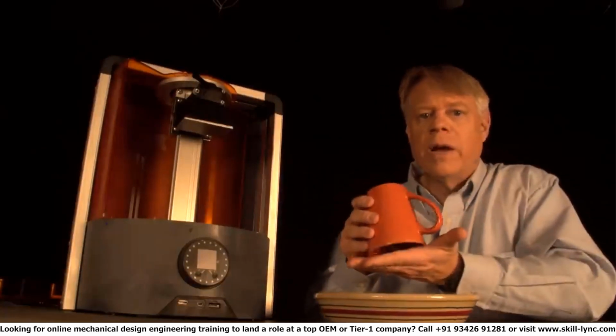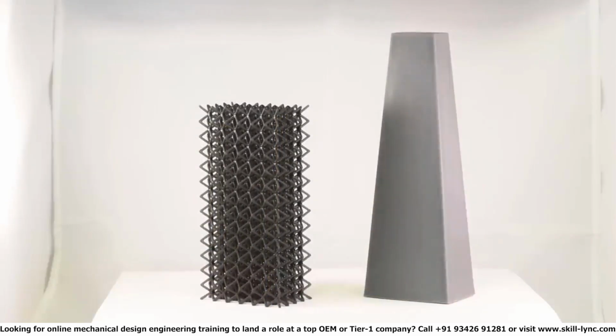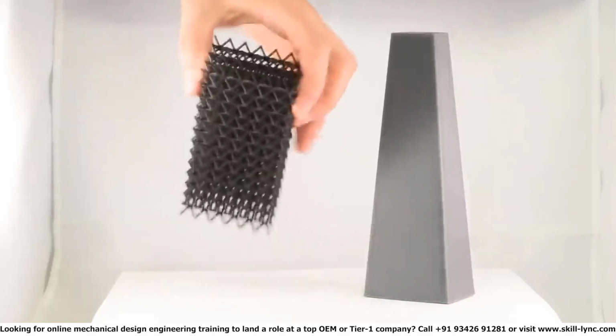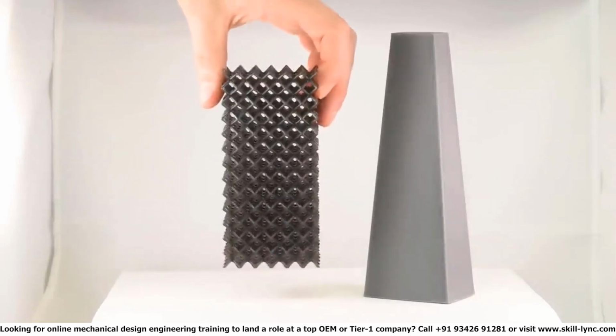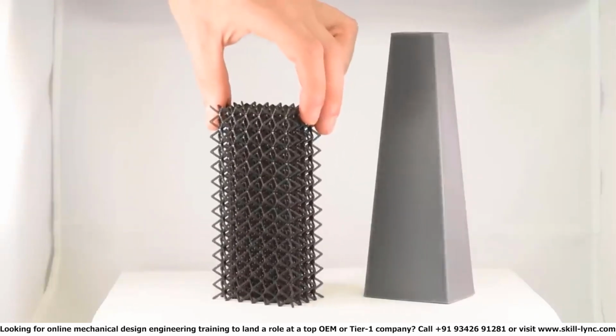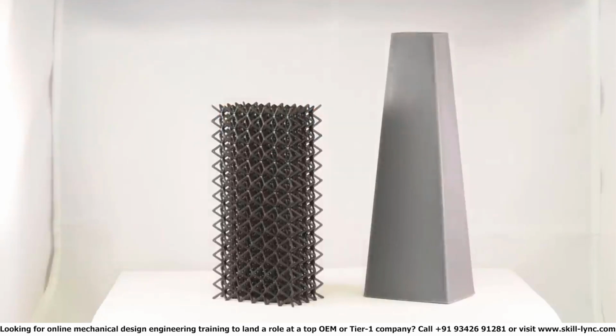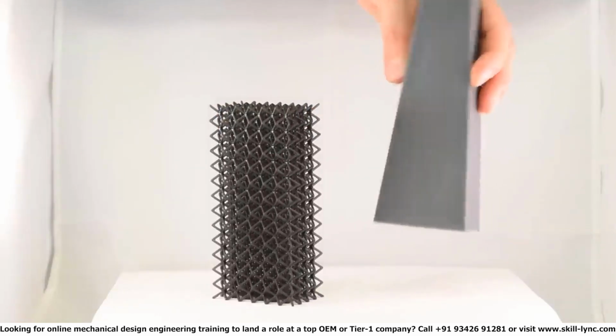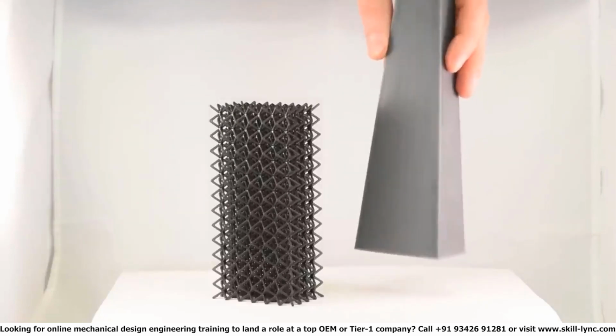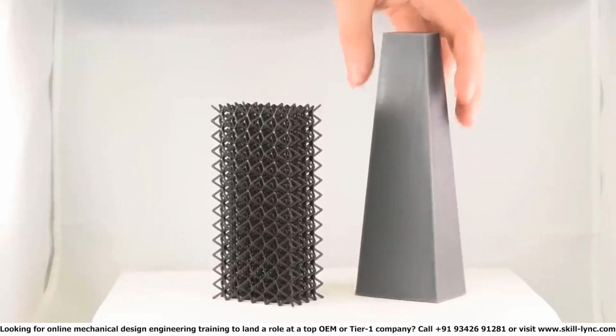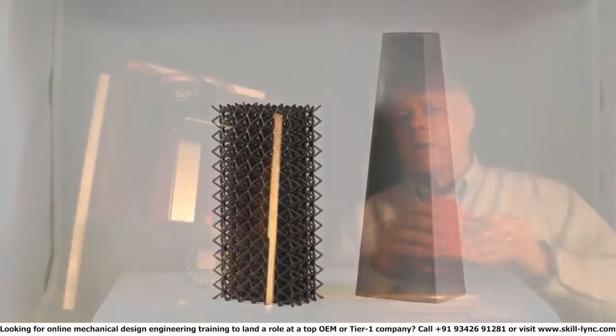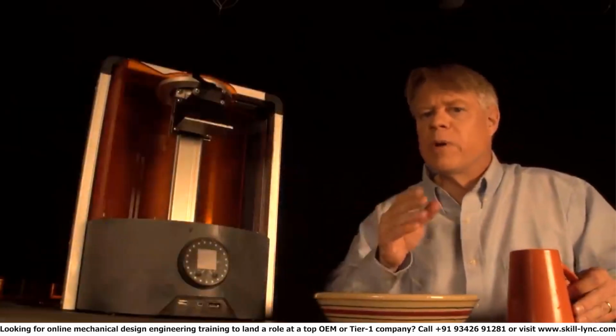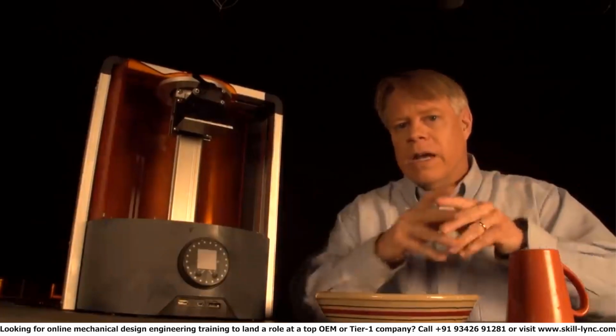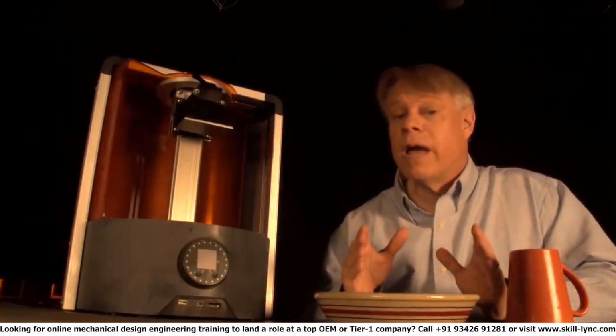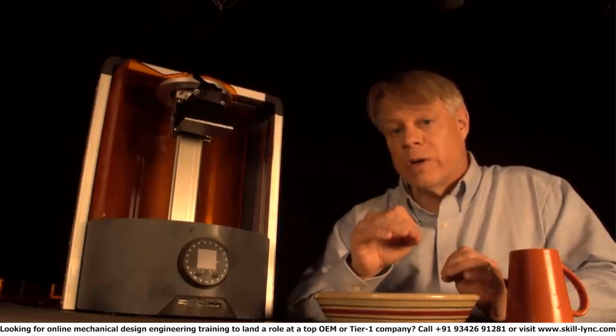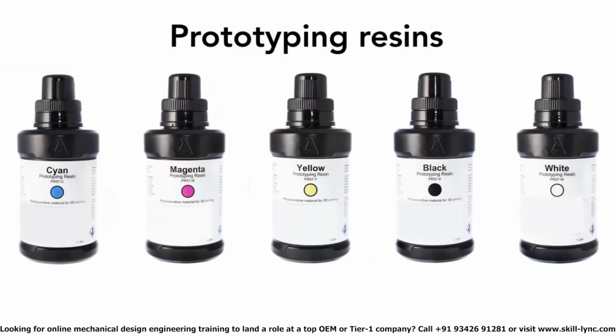It's sort of the same with selective laser melting, but that depends more on the particle diameter of the metal powder, right? Over here, because you're using liquid resin, the determining factor is the laser itself. In selective laser melting, the laser also has an effect, but usually the laser can be more accurate than the metal powder itself, and the laser can produce a thinner cross-sectional area than some of the metal particles themselves. So let's move on.